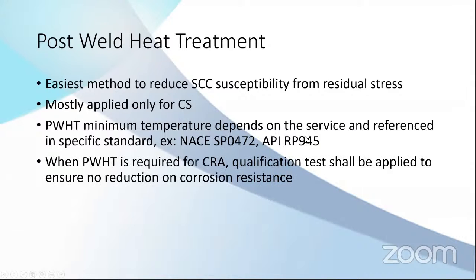And sometimes you cannot avoid it, but it's very rare. Sometimes you cannot avoid post-weld heat treatment of corrosion resistant alloys, maybe stainless steel, probably because of the code requirement or because of the thickness. Then what you can do is to qualify the welding parameters during the PQR. In the PQR, you need to do the qualification test.